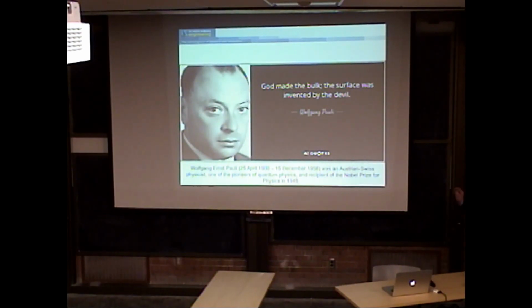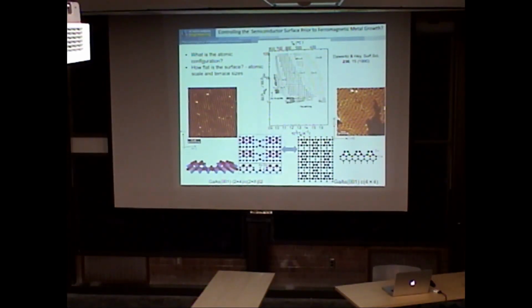So then, of course, I'm going to go to the next step. Okay? I showed you all the bulk. So if you believe in Wolfgang Pauli, God made the bulk, the surface was invented by the devil. Okay? It's a very good statement when you start doing surface science. Just remember that. So if I say I'm going to start with gallium arsenide, if I take the 001 surface of gallium arsenide, here's a phase diagram. Depending on the arsenic to gallium flux you have, I can get lots of different surface reconstructions on that surface.